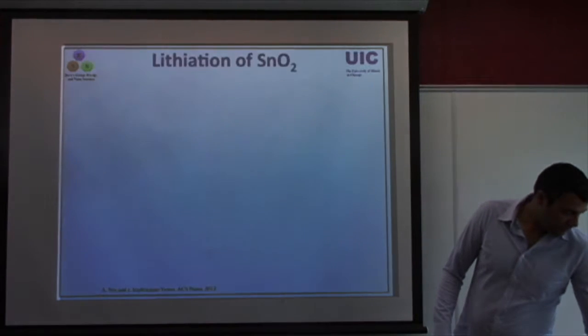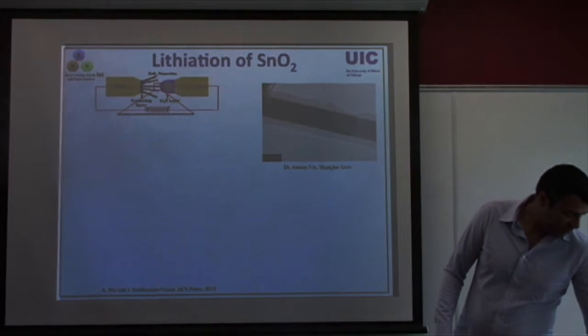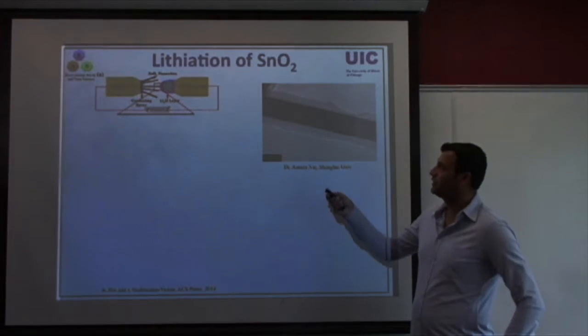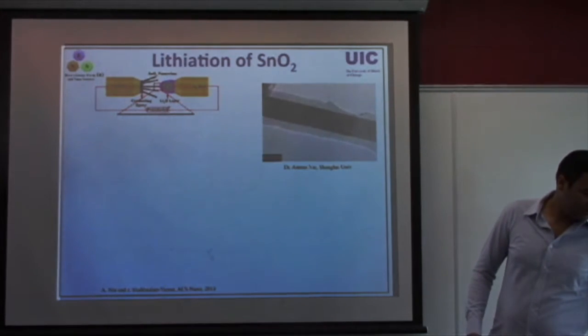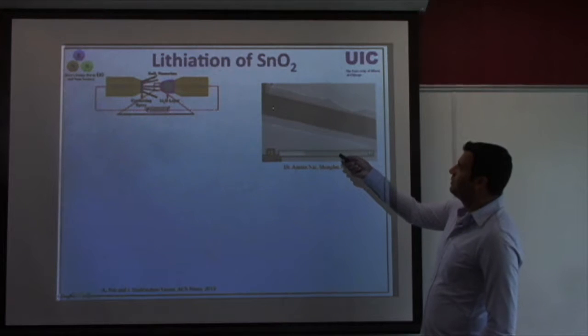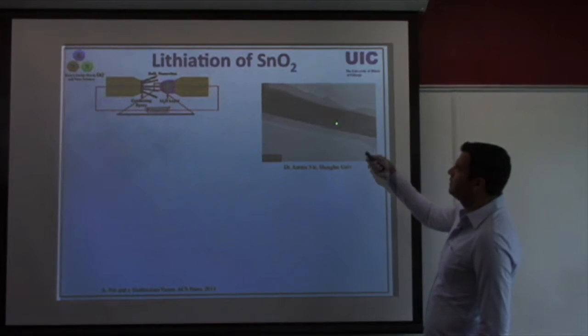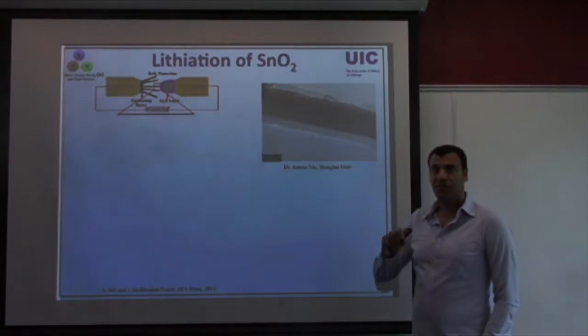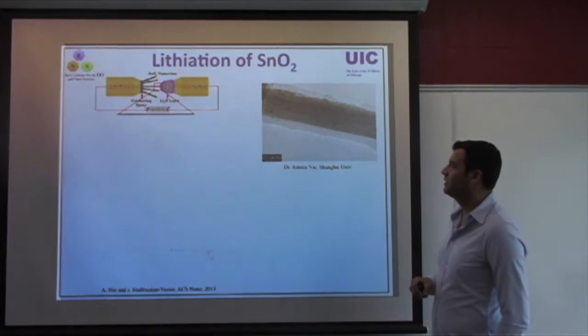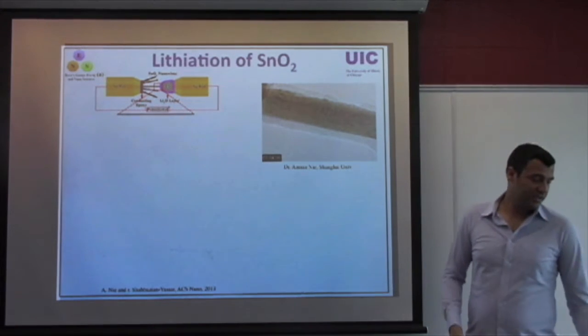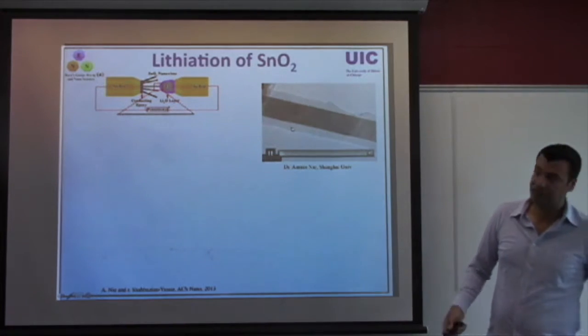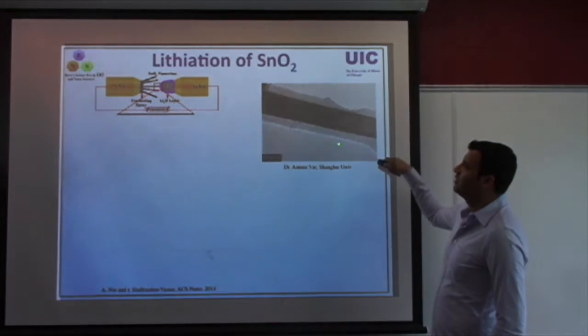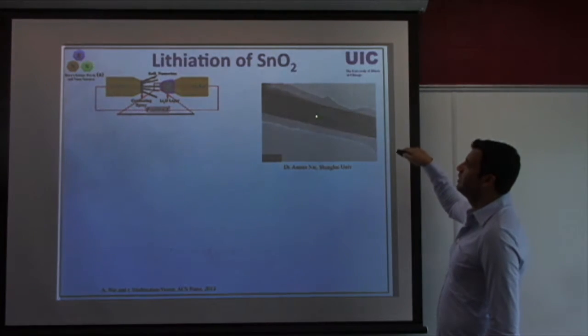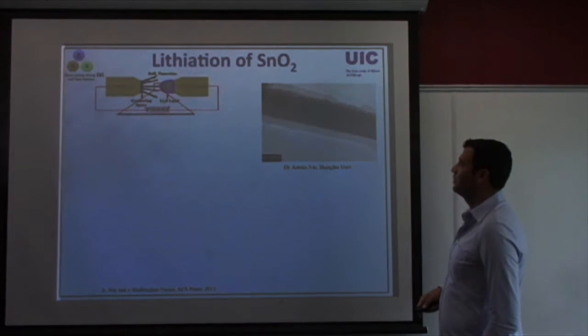So I'll show you an example of the work that my group did on a tin oxide sample. If you look into this material under lithium penetration, or the lithiation process, you see the formation of a variety of stripes in the sample, which indicates there is anisotropic lithiation, followed by a second phase of lithiation, which involves amorphization of the whole structure followed by lithiation in anisotropic directions.